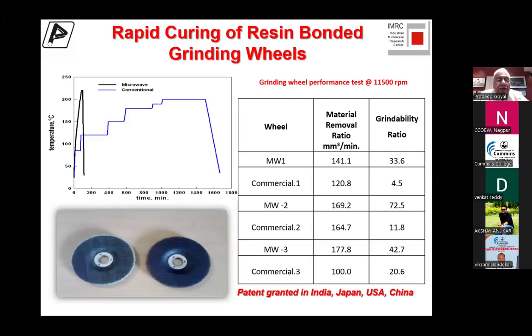So that is why if you see the stepwise process going from 80 degrees to 120 to 150 to 180, and slowly you keep heating this grinding wheel, keep it at a temperature, and after about 1600 minutes, you have baked the grinding wheel. But when we did it in a microwave environment, look at the black graph. We went up rapidly from room temperature up to about 230 degrees and cooled it. And nothing happened. It didn't crack. Nothing happened to the product.